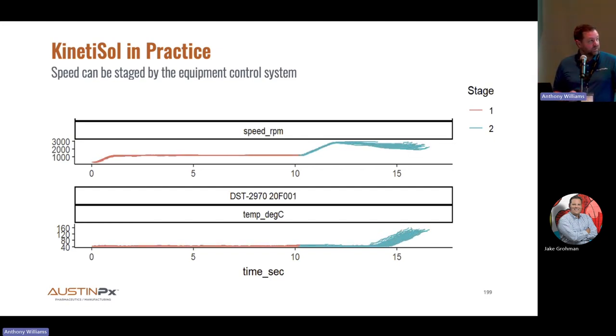And you can see, this was a couple hundred shots, and the only real variation is in where this inflection point happens. And that is what we call the sort of when the process kicks off. When you're watching the machines run tomorrow, don't forget to listen, because you can hear this. When the mixer starts to become bogged down by the energy required to keep its motion, the whole viscoelastic nature of the system changes, and you can hear it in the machine.